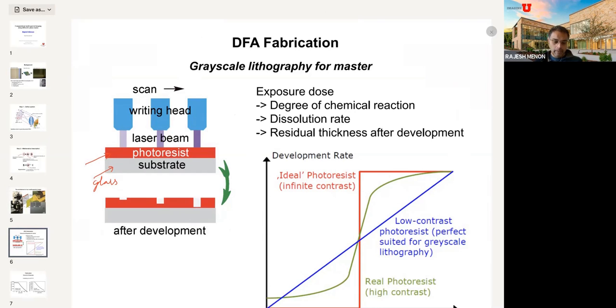And then we put a laser beam with different power. So here I have more light, you have less light, and you have even more light. So that's why it gets darker. Now, by changing the energy that I'm depositing into the photoresist, after a development process, it's a chemical process, I can create different topographies. So here I have more energy. Here I have slightly higher energy, and this is my standard energy. So I can create deeper and deeper structures.